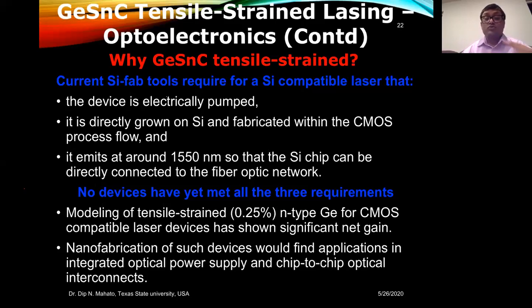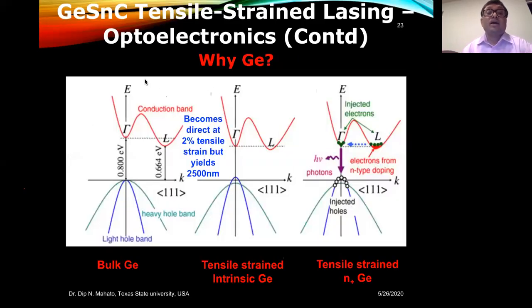So then 0.25% tensile strain, the modeling data shows, would do. But there are so many challenges there. This is something I wanted to show. This is already something I talked about, the germanium direct band gap and indirect band gap. And then you want to make it tensile strained, so there is a slight decrease in the gap between the direct and indirect. And then you have to do the calculation of how many injected electrons and how many injected holes you can get, so it gives you the light that you want, to make the device integrated to get the laser.